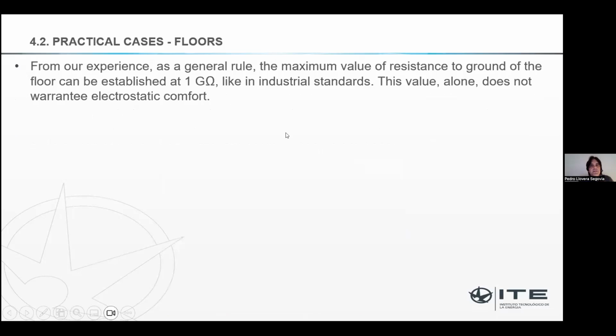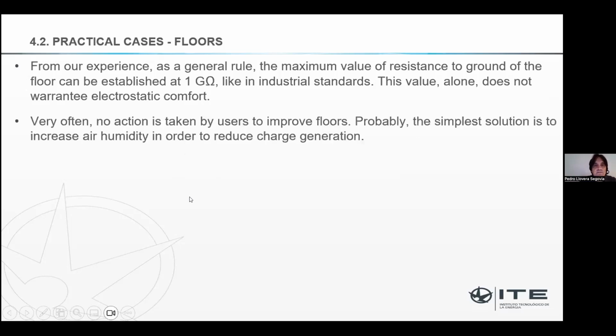From our experience, in general, the rule of 1 gigaohm, 10 to the 9 ohms, like in industrial standards, is okay. It has also been taken in this new standard coming, but it alone does not warrant electrostatic comfort for floors. It depends also on the interaction with people. That's a very, very well-known problem with electrostatics. Probably the simple solution is to improve air humidity in order to reduce charge generation.